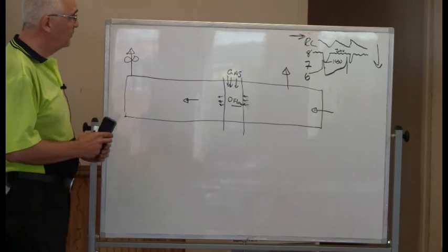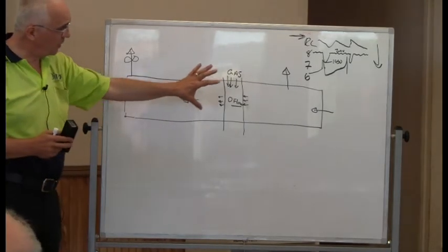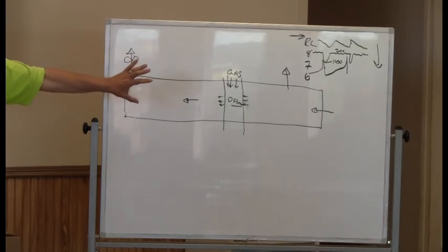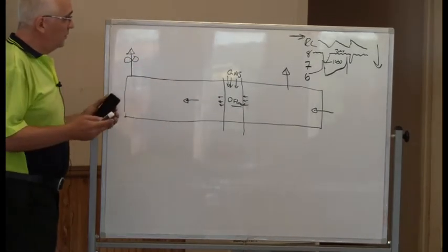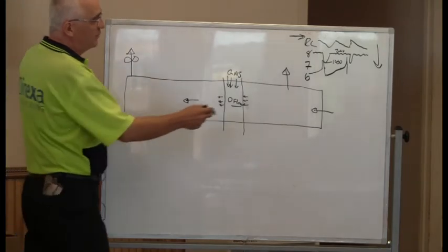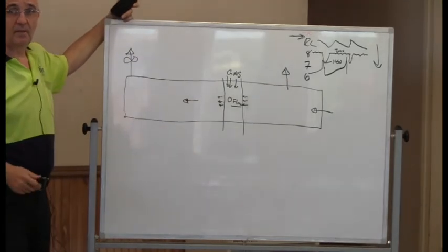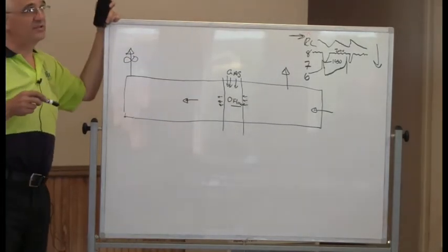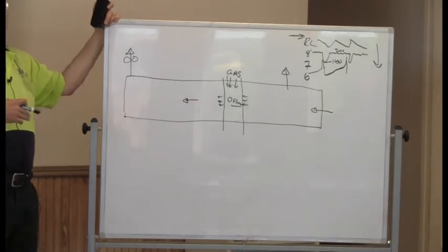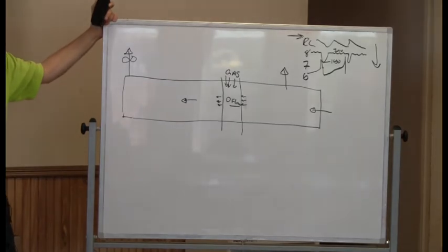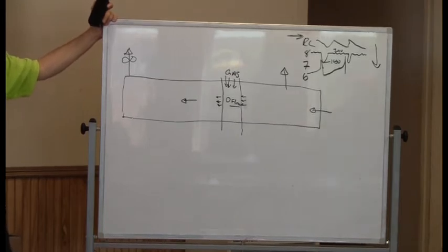So let me first talk about how to balance the flow here. The temptation to have zero flow here is to decrease everything. The problem is, if you push every 40 minutes and you flash for 5 minutes, it means that 35 minutes you are doing normal kiln operation and 5 minutes you are doing flashing operation.